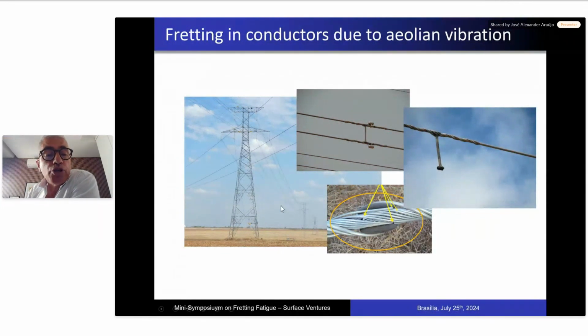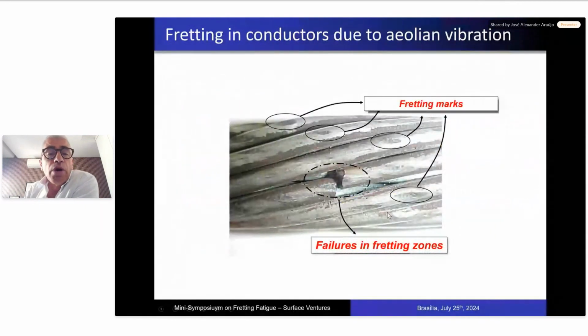This caused big damage to the transmission line because of the penalties due to the sudden stop in the transmission of energy. The regulator in Brazil imposed very heavy penalties for that. So it had a very bad financial result. This is the typical form of the cracks in these problems. So you see that they always start within fretting marks, and these fretting marks look like that.